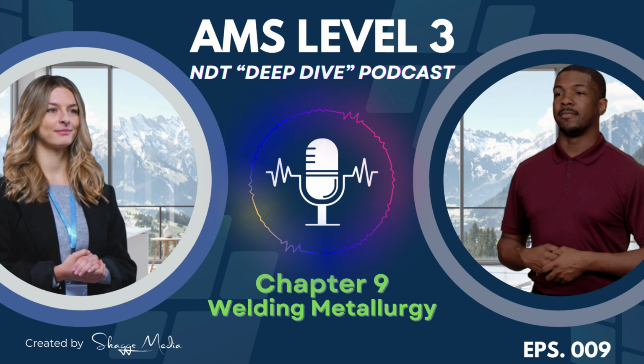So how do we relieve those locked-in stresses? The most common way is thermal stress relief, which is a type of post-weld heat treatment, or PWHT. You heat the entire welded component uniformly in a furnace to a temperature high enough to soften the metal slightly, but again, staying below that critical A1 transformation temperature, hold it there for a specific time based on thickness, and then cool it down very slowly and uniformly. This allows the metal to creep or relax on a micro level, reducing those internal stresses.